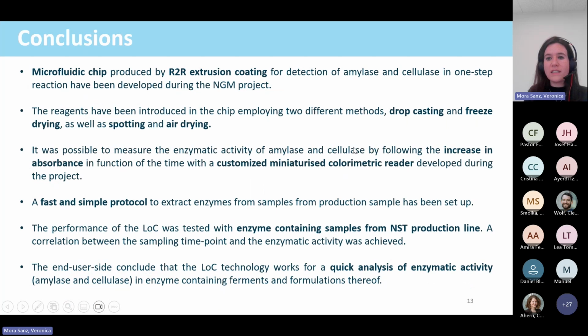So the conclusions of this work are that during the NextGenMicrofluidic project, we have been able to produce a microfluidic chip produced by roll-to-roll extrusion coating for the detection of amylase and cellulase in one step. We have also tested two methods to integrate the reagents in the chip. On the one hand, drop casting and freeze drying, and on the other hand, spotting followed by air drying.